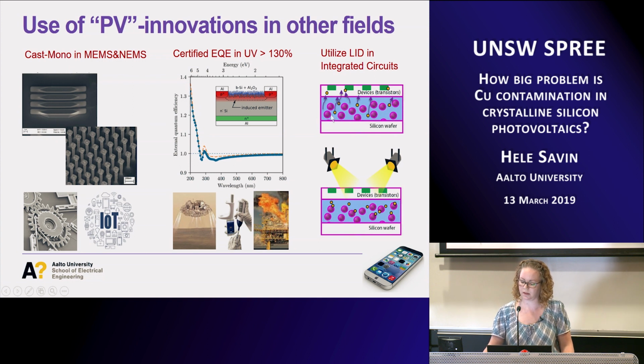They are trying to use different types of gettering sites inside the bulk, which work quite nicely, for instance, for iron, but not so efficiently with copper. But the solution is actually to use the fact that copper will react with light, and it will form some very stable defects when exposed to light. So what the industry is actually doing is shining lights on their chips, when the copper hasn't yet had time to diffuse to the surfaces. If they are exposed to illumination by different types of lamps, the copper will form specific defects in the bulk, and these will be very stable and won't diffuse to the surfaces.